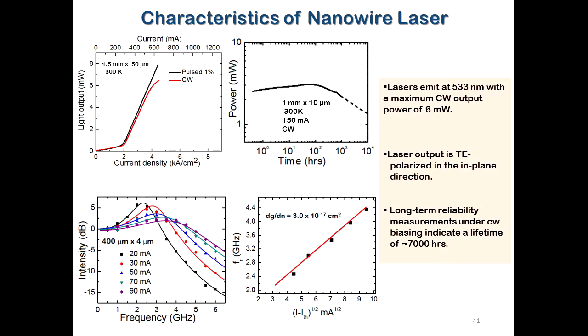So this is a laser on 001 silicon, very reliable. We actually measured the reliability, and the lifetime is roughly about 7,000 hours CW. And we even measured the modulation bandwidth, so they can be modulated, and so on. And there we are. And I'll talk more about this tomorrow.